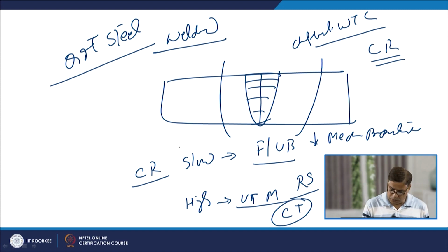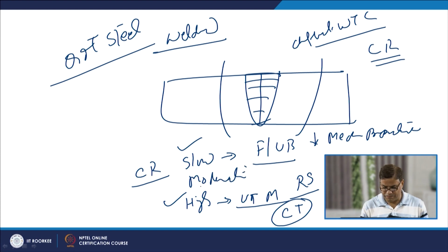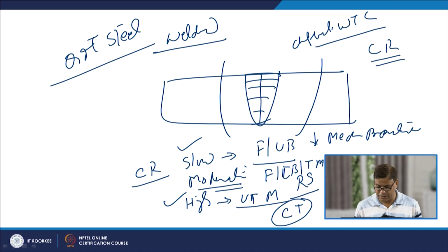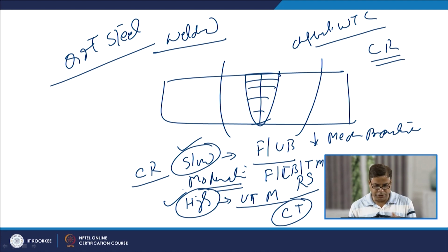So, neither too high a cooling rate nor too low a cooling rate is needed during welding, and that is why moderate cooling rates need to be used, so that we get ferrite, bainite, lower bainite and maybe tempered, auto tempered martensite. So that we have a reasonable combination of yield strength and toughness, and unnecessary residual stresses, which would increase the cracking tendency, are not developed, and the embrittlement tendency is also reduced. So, neither too high nor too low cooling rates need to be used during welding.